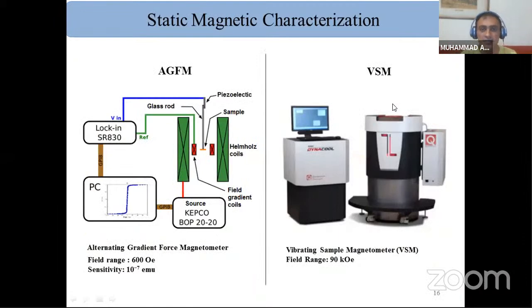Static magnetization characterization was done with the help of AGFM and VSM. The AGFM has a field range of 600 oersted, while the sensitivity is 10^-7, which is enough for measuring the static characterization in this project. If we need a high field, we can use a vibrating sample magnetometer with a field range of 90 kilo-oersted.